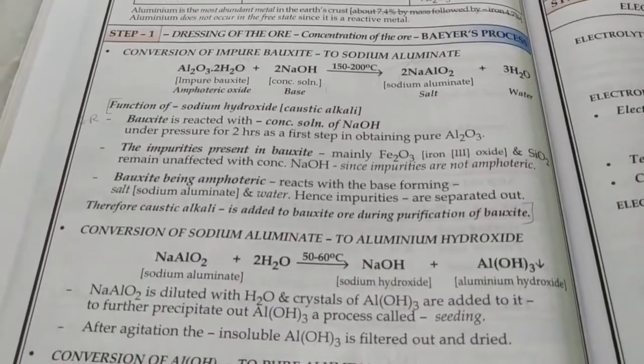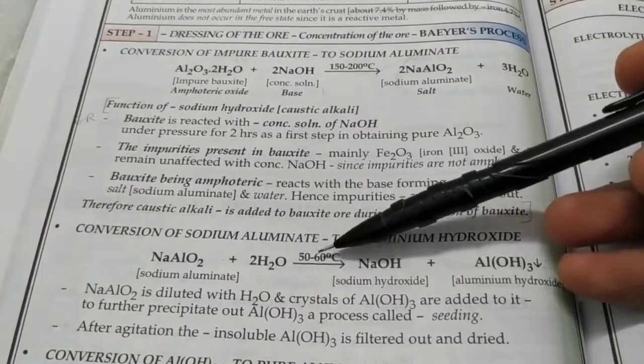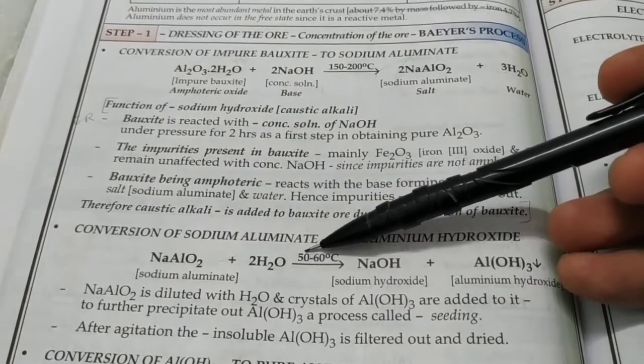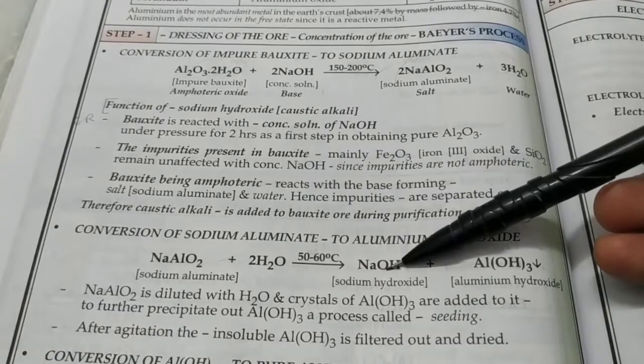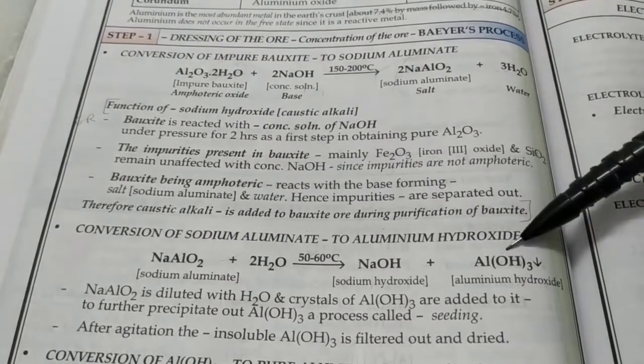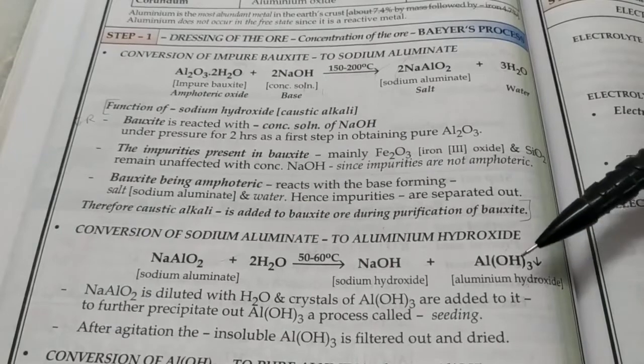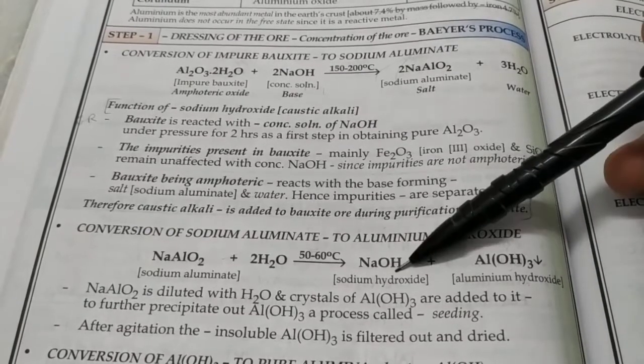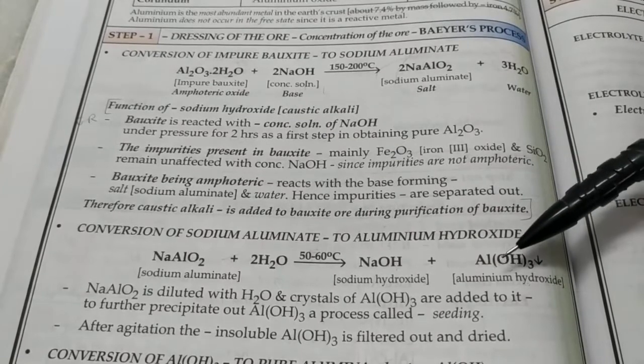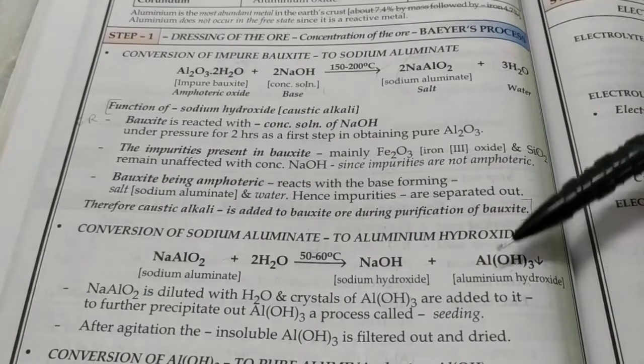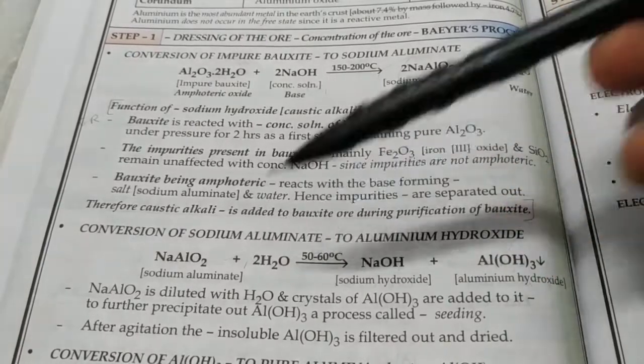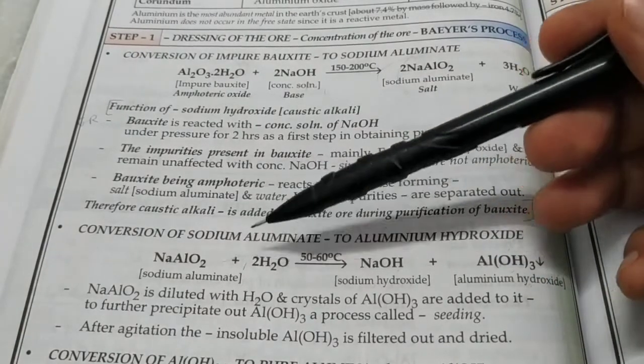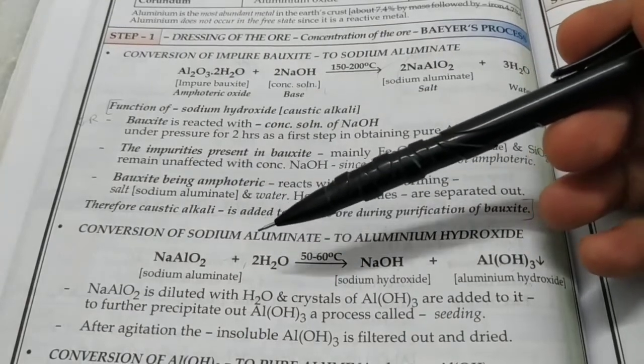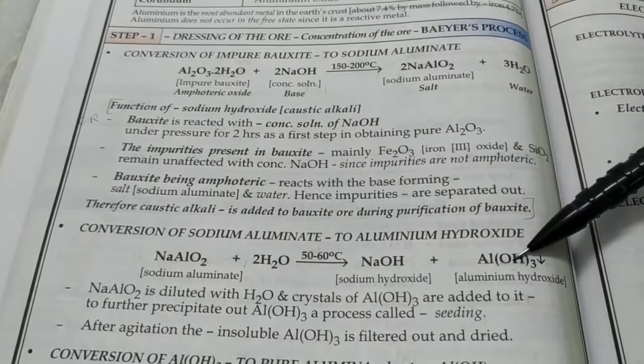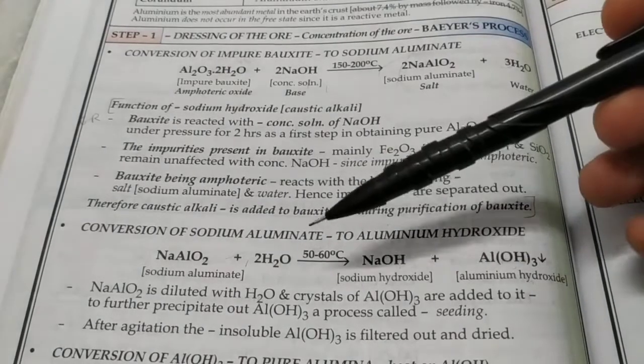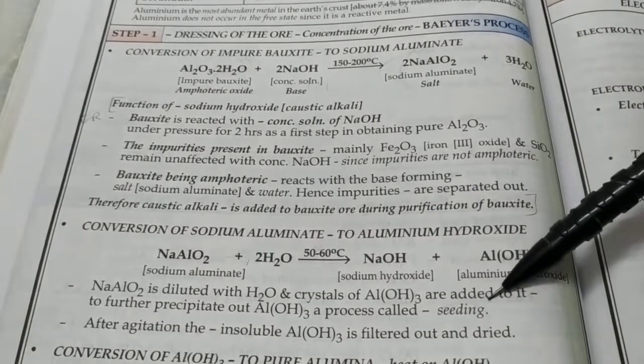So the next step is I'm going to heat the solution at a moderate temperature, warm environment of 50-60 degrees Celsius. So I'll get my sodium hydroxide back, which I had used earlier. But now I will get a precipitate of aluminium hydroxide. That's cool because now I can filter it again and separate it from sodium hydroxide. And to hasten this process of precipitation, you can add a few crystals of aluminium hydroxide already in the solution. Looking at the crystals of aluminium hydroxide, other molecules will be motivated and they will also form aluminium hydroxide precipitate. This addition of a few crystals of aluminium hydroxide in it is called seeding.